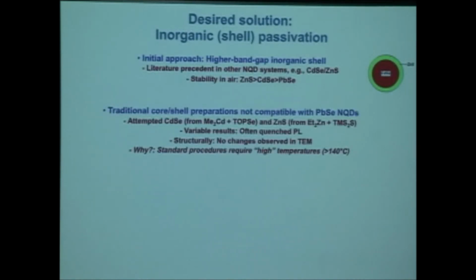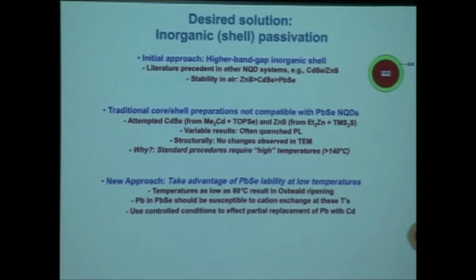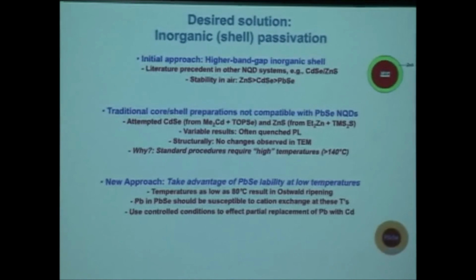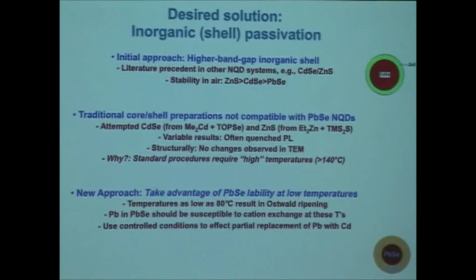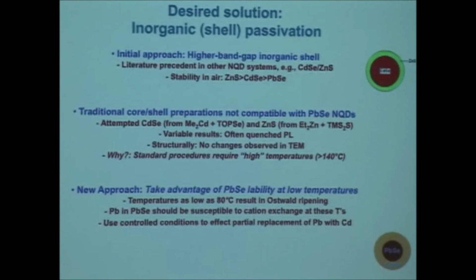Anyway, of course everyone wants an inorganic shell approach. You can improve your stability and your efficiencies and so on. The problem with lead selenide is the high lability of the lead and the chalcogenide atoms. When you try to apply conventional shell growth techniques that rely on relatively high temperatures, the lead selenides tend to aggregate and grow and so forth, so traditional methods would not work. So we used a new approach, where we utilize a cation exchange to create a cadmium selenide shell over lead selenide.